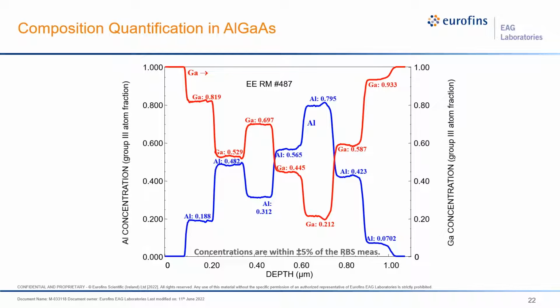This shows the aluminum and gallium profiles in a stair-step sample with multiple layers of aluminum gallium arsenide and gallium arsenide layers, with aluminum group 3 fractions ranging from 0.07 to 0.79. And note that all of the SIMS determined compositions are within 5 relative % of the values determined by Rutherford backscattering spectrometry, which is quantitative from first principles.